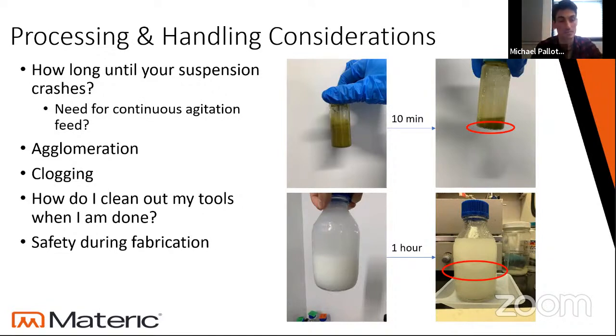But jumping up to the two images on the top, sometimes when working with nanoparticles, we only have 10 minutes. Once that final solution is prepped, we only have 10 minutes to pour it into our electrospinning system, whether it's the Inovenso or our needleless system, and then to spin it at the right conditions before it drops out. We'd used about 80% of that solution on the left, so we were able to see that with that 20% left, the solids start to drop out of solution at the bottom.